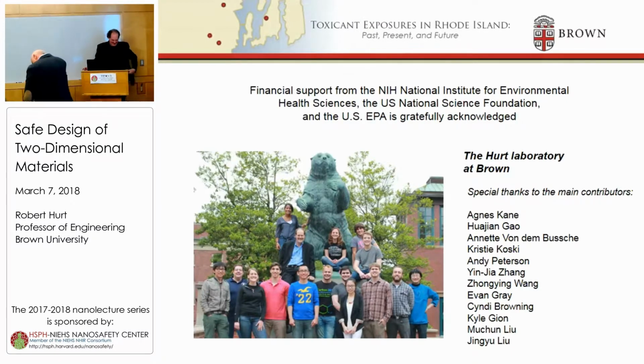Thank you for the presentation. Very, very exciting data. I have a question regarding the dissolution of the materials that you showed. Have you looked into, or is it even possible, when you dissolve these materials selectively, to change either the band gap, so you bring them closer to the redox potential, so the material starts not to be toxic based on redox, but it ends up to be, or similarly, to make the edges of this material more jagged and more sharp, so it can actually enhance the uptake of the materials. Have you looked into that?